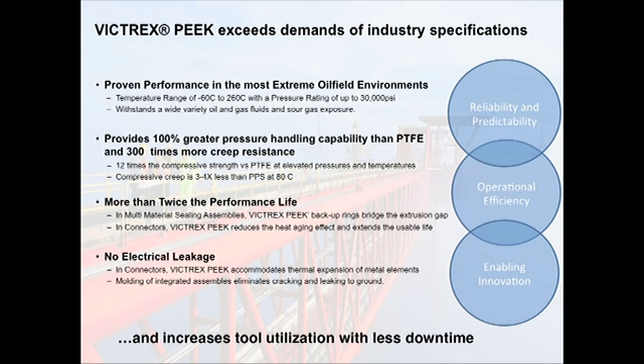PEEK's operating temperature range is -60 to 260 C with a pressure rating of up to 30,000 psi, and it withstands a wide variety of oil and gas fluids and sour gas exposure. It provides 100% greater pressure handling capability than PTFE and 300 times more creep resistance. PEEK has 12 times the compressive strength versus PTFE at elevated temperatures and pressures. Its compressive creep is 3 to 4 times less than PPS at 80 degrees C,